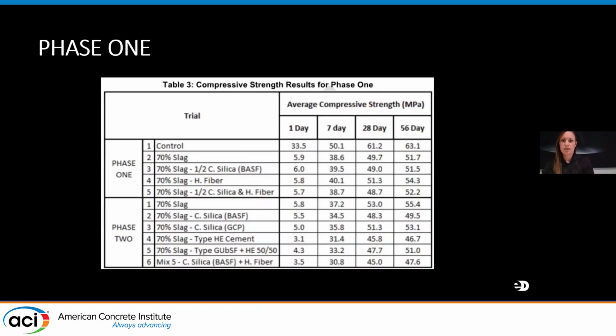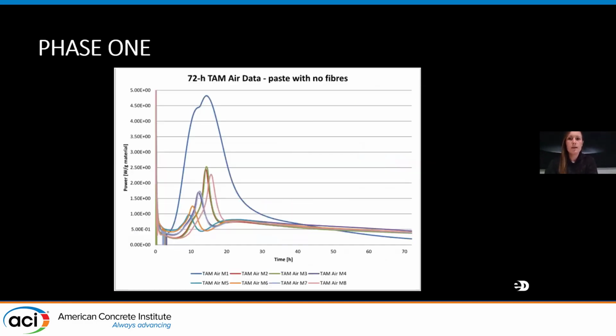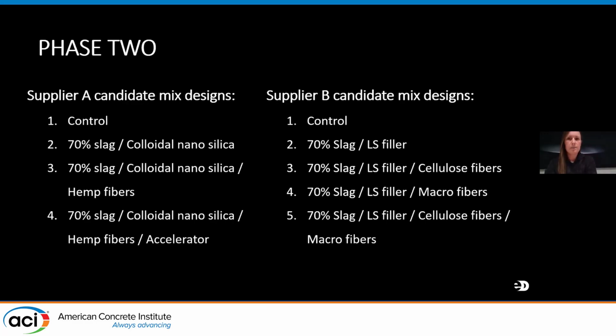The 28-day compressive strength results from the trials I had just shown demonstrated that all of the mixes exceeded the 35 MPa requirement. So you can see from the 28-day results. In order to verify the performance of the candidate mixes, the paste components were tested using TAM Air calorimeters for the heat of hydration over a period of 72 hours. You can see that the high volume slag mixes are a lot lower, well below the control mix. And I will show you the in-place measurements as well.